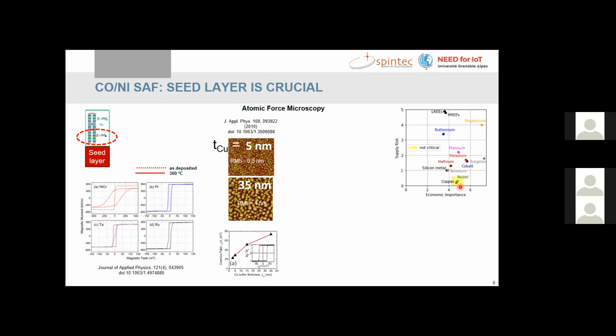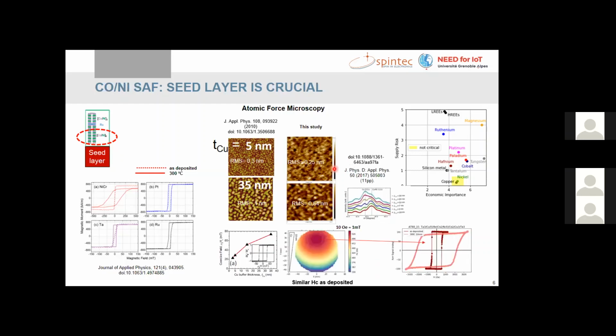So there has been some study evaluating what is the roughness that grows when having a thick copper buffer layer. And we also did this type of study and observed sufficiently low roughness for the type of thickness of copper that will provide good 111 texture. So we also studied a little bit the magnetic properties of such multilayers first, and we saw that after annealing, we were able to get even a much higher coercive field for these multilayers, which was a positive result.